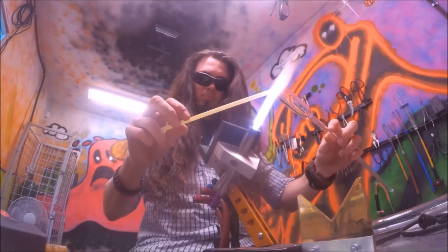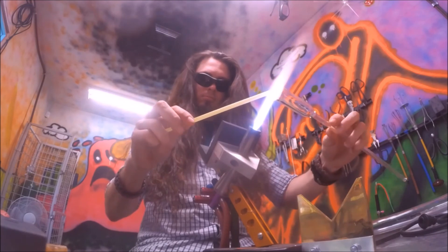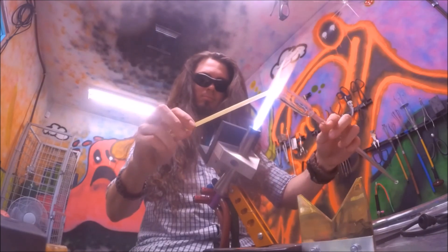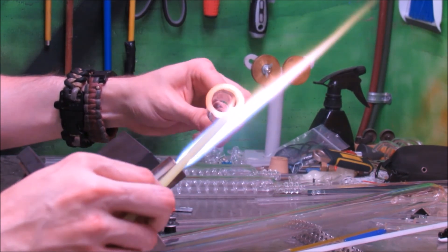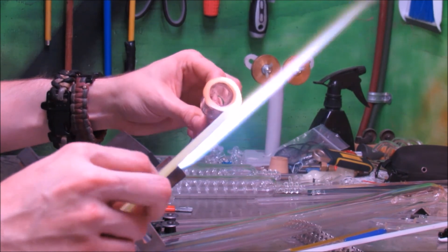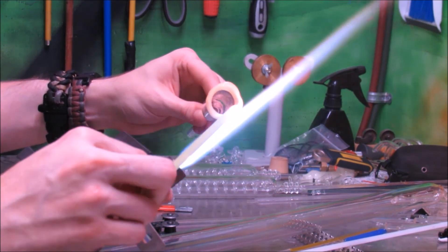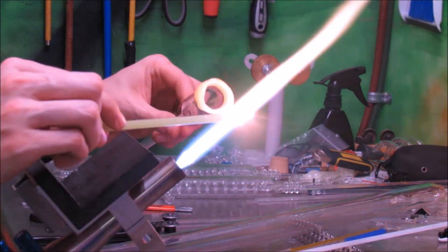This prevents air bubbles from being trapped. Make sure the end of the blank is square and the wall thickness is even — it will help for an even edge when blown out. Coil potting takes a lot of practice, but it is pretty straightforward. Evenly heating the rod and twisting to apply. Overheating and over twisting will make the walls of the coil start to close in.